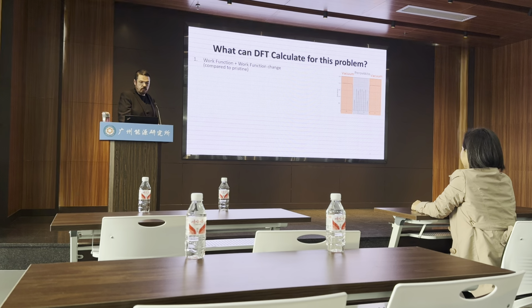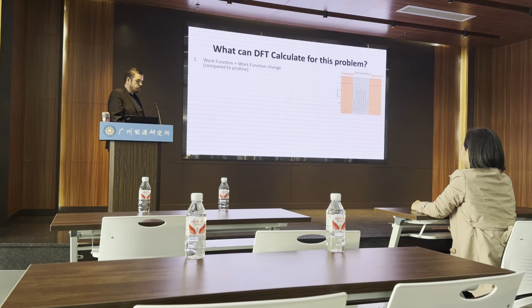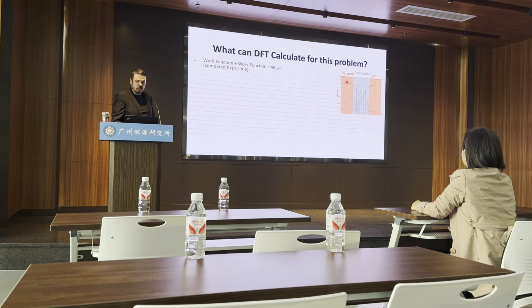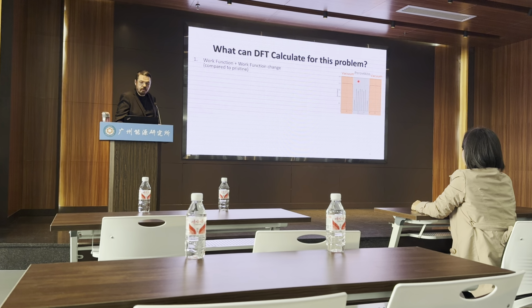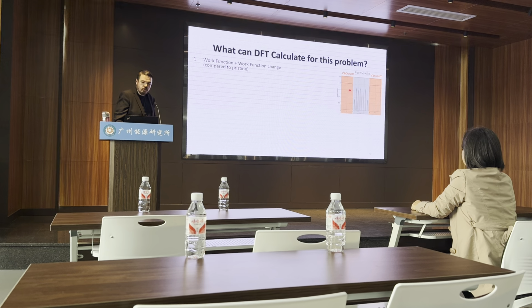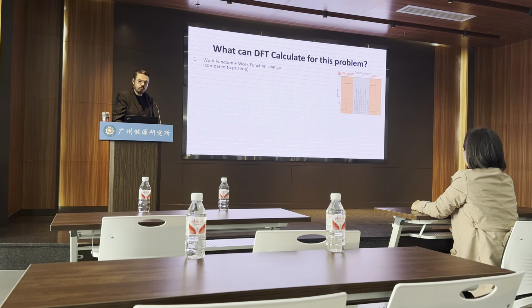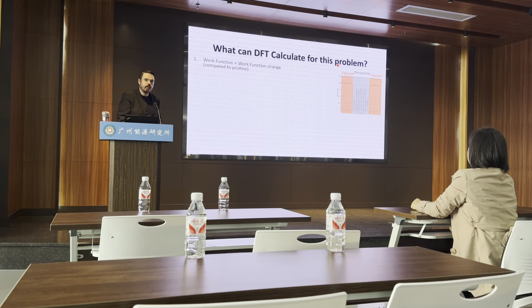It can calculate the work function and how the work function changes. And we always compare to pristine. So pristine, on the right-hand side here, you can see the vacuum is in the orange area. The perovskite itself is the gray area. And we make the terminations symmetric. And this is very important, because now we can see how the vacuum changes by introducing asymmetry.